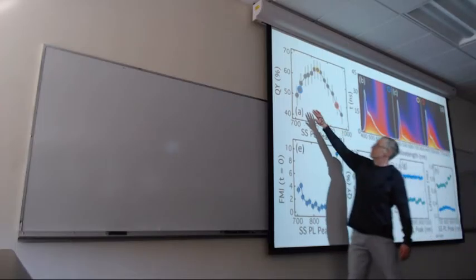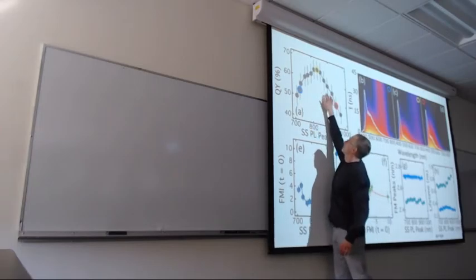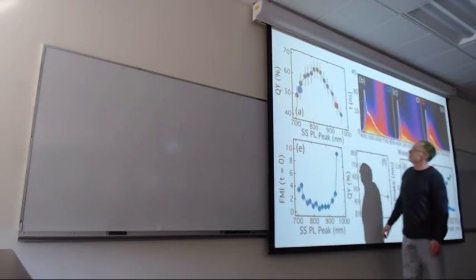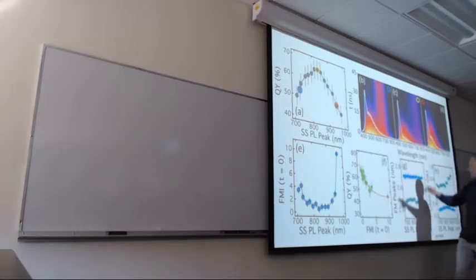Inspirations from experiment that may launch new calculations? Well, yeah, I'm trying to work this out. These are quantum dots we're making out of silicon. We spin them into fractions, and you see the quantum yield has a sweet spot, something we're still trying to understand. We sent these fractions to Rich Dowler, and he did very fast PL decay spectroscopy. So we see this sub-nanosecond.